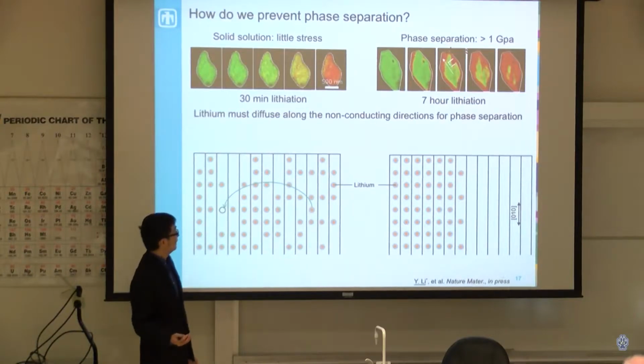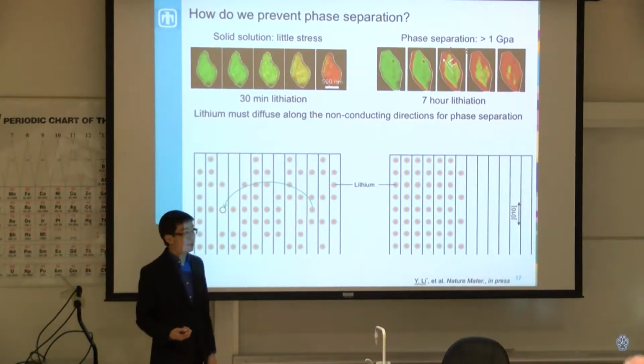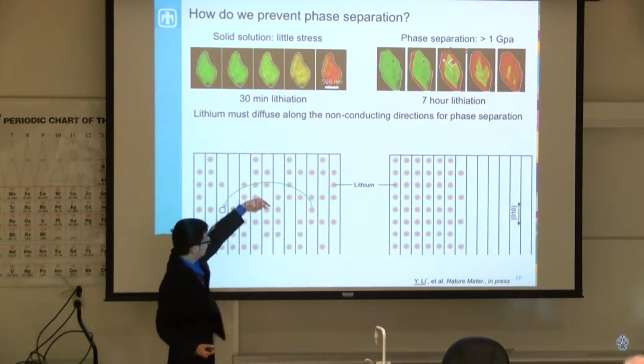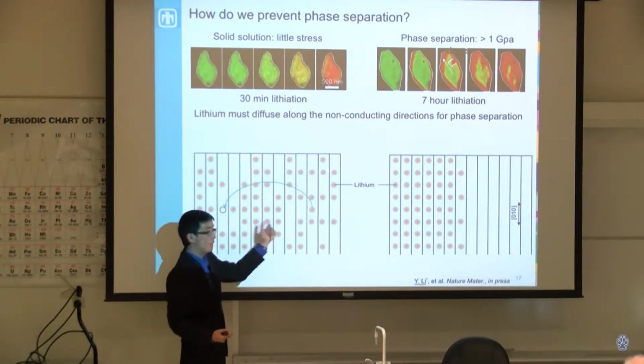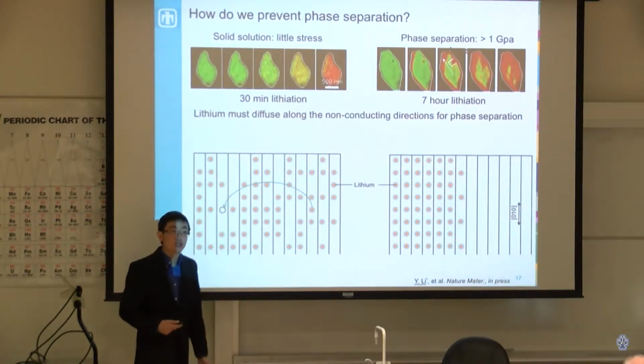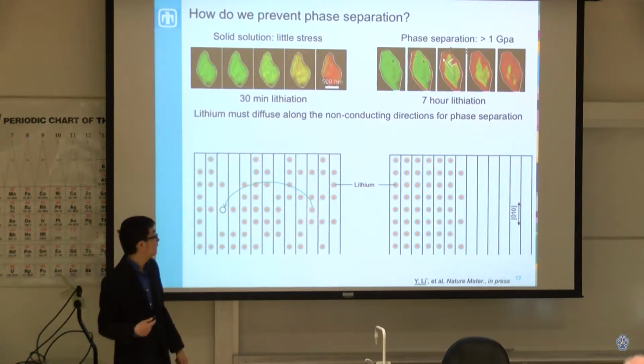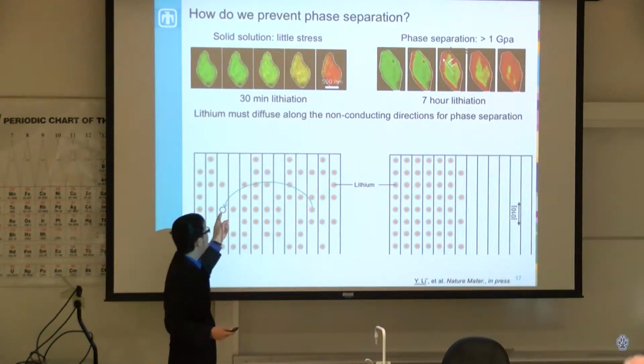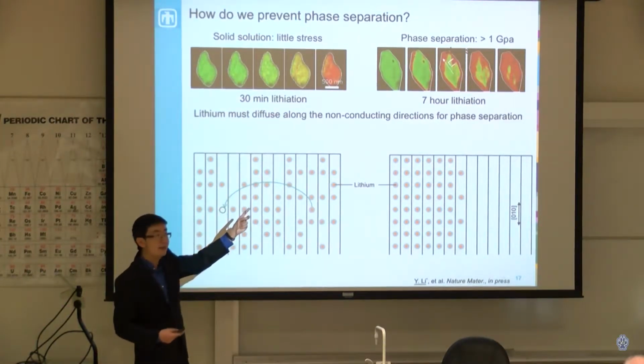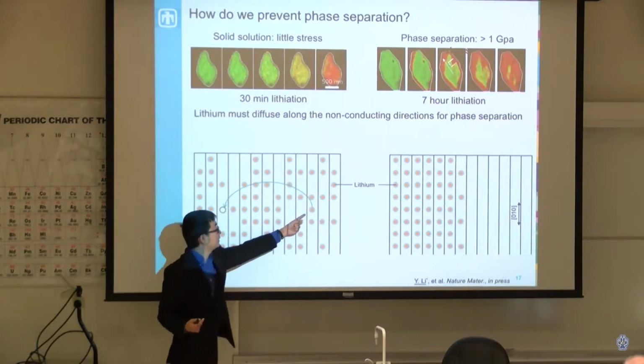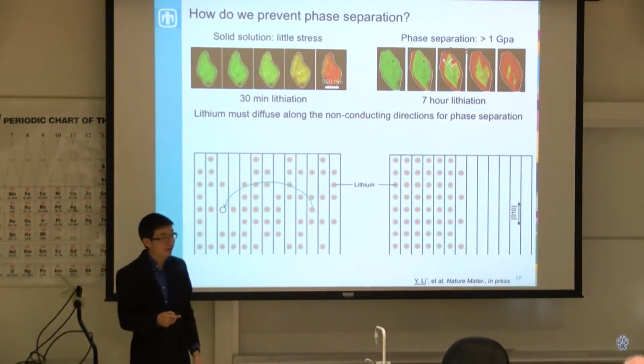However, what's also interesting in this material is that it's a one-dimensional lithium conductor. So in principle, lithium can move up and down, but it should not be able to move left and right. Our goal is to understand the mechanism of how lithium goes from here to here, which we clearly see, even though the theory says lithium shouldn't be able to move this way at all.